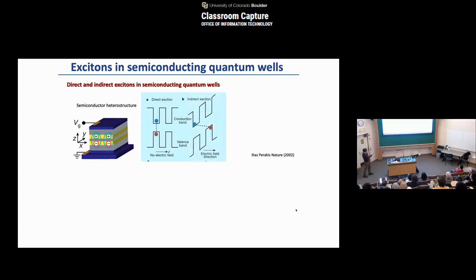But then you bias the quantum well with external voltages and tilt this quantum well. What can happen is that this intra-layer exciton can dissociate, and either the electron or hole moves to the opposite layer to form its own majority carriers and happily stay there, right? But then there's a residual Coulomb interaction between these two that can still bind them across this interlayer and form so-called interlayer excitons in this way.